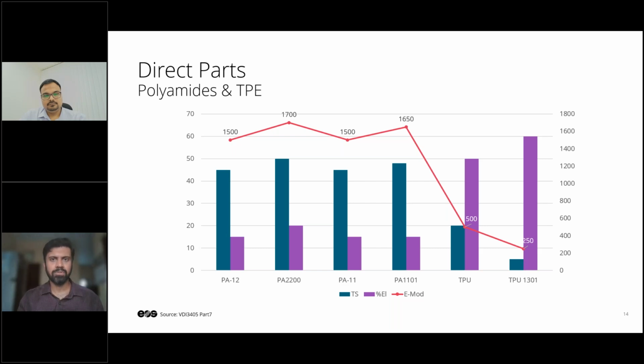The one is for material extrusion, fused filament fabrication. The other is laser sintering, right? I don't say this, but the standard says that these are the two major, widely accepted processes. And if you compare these expected properties as per this standard and EOS, properties match almost 1:1, right? And even when you compare with some of the injection molding standards for nylon 11 and nylon 12, properties are very similar. 45 megapascals that you get in injection molding, you get 48 megapascals here in laser sintering. There's marginal difference. So that is where the technology is going.